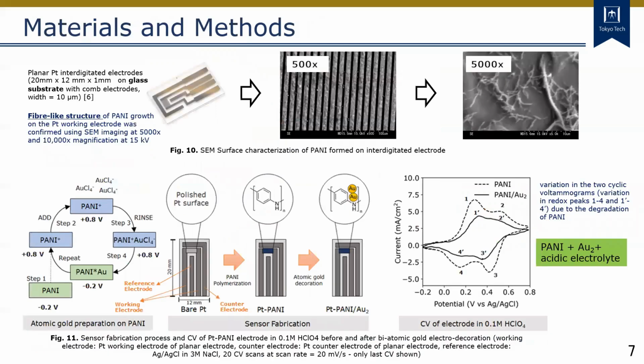Let's look at the materials and methods. Commercially available platinum interdigitated electrodes were electropolymerized to form polyaniline film. The fibre-like structure was confirmed with scanning electron microscopy at 5,000 and 10,000 magnifications. Figure 11 shows the sequence of the sensor fabrication process. In the case of formation of PANI, the typical cyclic voltammogram of PANI is shown.